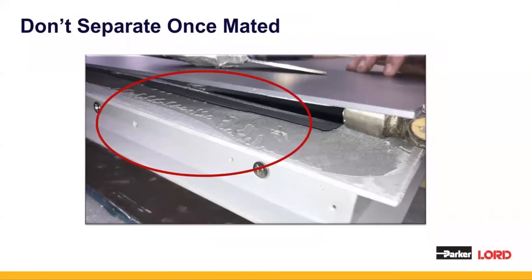Once your parts are mated, it's important that they don't come apart. If the bond line separates and becomes remated, you can actually entrap air. And air entrapment will certainly cause failures, sometimes as quickly as coming straight out of the oven. In this slide, there's a picture of what air entrapment looks like. You can see splatter marks on top of the squeezed out bead of adhesive. And this is something you don't want to see. This means that there has been air that's been trapped in and the panel has sprung up and squeezed back down. What you want to see is actually just a smooth, even layer of adhesive.